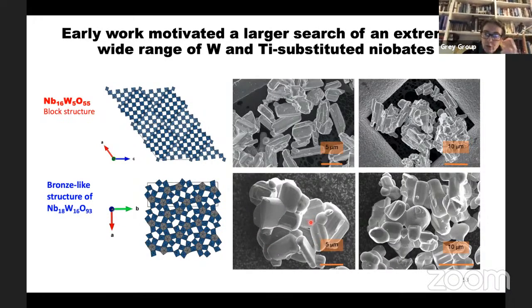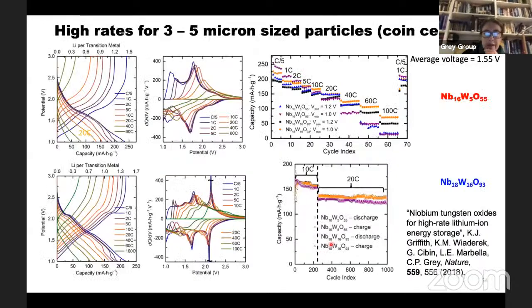So these are so-called single crystal morphologies, where they're semi-agglomerated, but not in the same way I was showing you before. And then what we can do is to test them against lithium metal and test how fast they cycle. And so this is an example now for the niobium 16 compound. So when you cycle slowly, you get a capacity of about 250 milliamperes per gram. But when you're cycling up at so-called 60C, you can still see that you get quite a reasonable capacity.